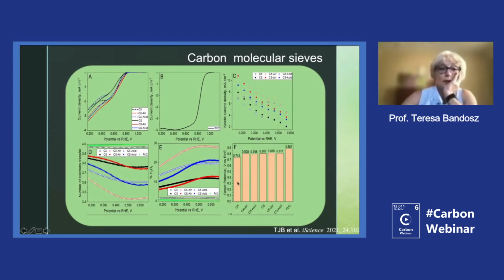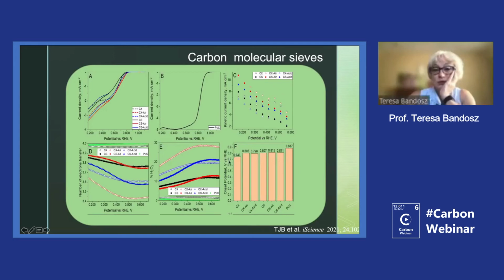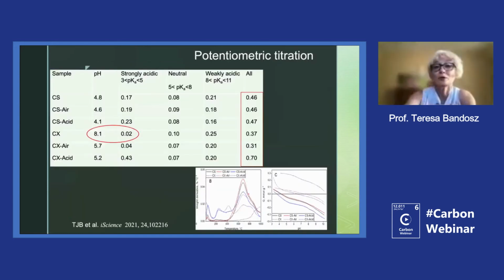So the Carboxen, which has the high volume of the pores, is not really there. But when we look at the onset potential, the Carboxen was not really very good. It was the worst of them, and all the others have similar values. So of course, the question is why, and it was why, and maybe it is still why. Okay, how to explain this? We know that working on carbon and understanding what's going on is not very easy, because we do not have a method which could give us detailed information about what is really on the surface.